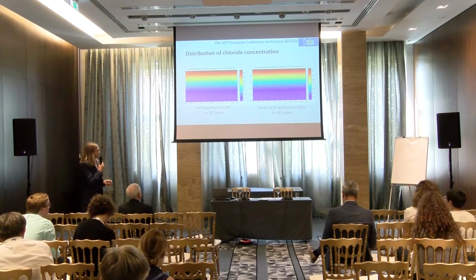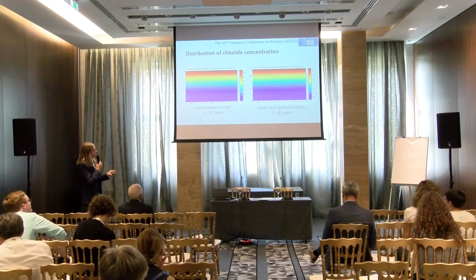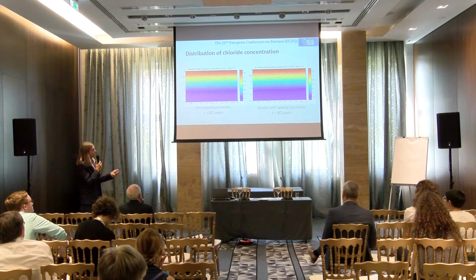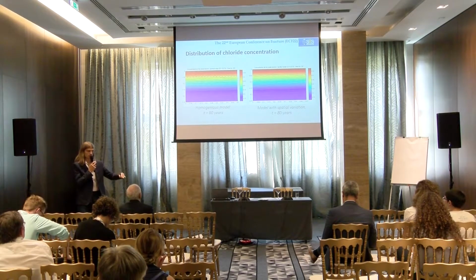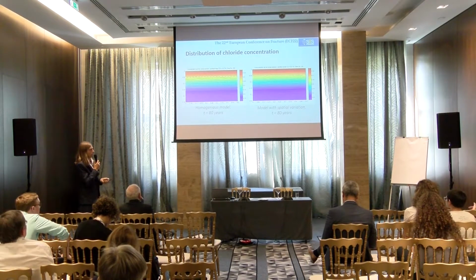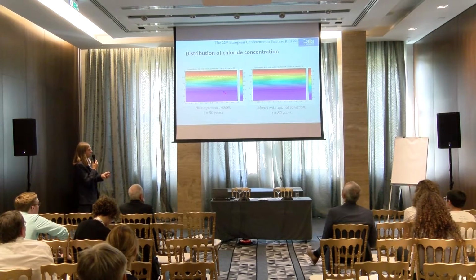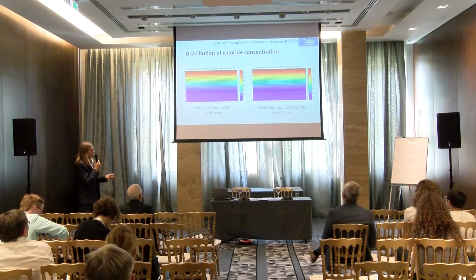So this is a result of the simulation. Two models. One is the homogeneous, the other is heterogeneous. Concentration of the chlorides is the loading from the surface. Here, the dashed white line represents the possible level of the steel reinforcement that is prone to corrosion. And this is actually the depth where we analyze the concentration of chloride. In the homogeneous model, you can find that the lines are parallel. And here in the heterogeneous, you can find out that the isolines are not parallel. It means there is to some extent heterogeneity going on.